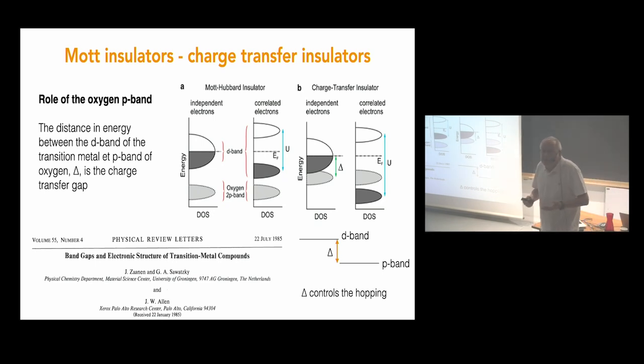And you have two extreme situations. The first one is here, when your oxygen p band is way below the d band of the transition metal, and you switch on interaction and you go to the Mott insulating state. The gap is between the two parts of the d band, and this gap is U, and this is a Mott insulator.